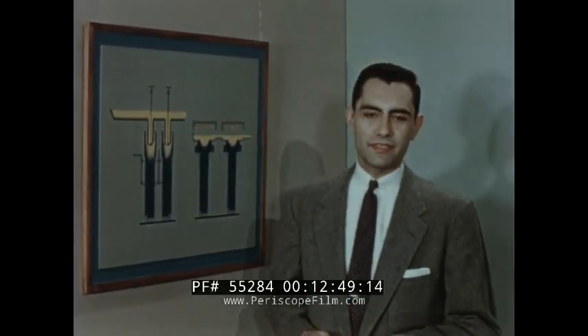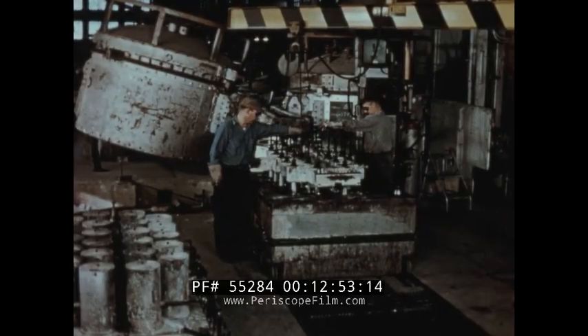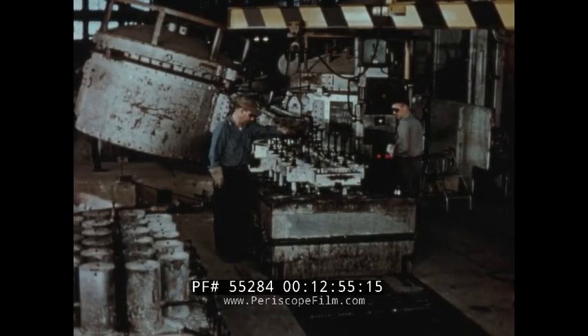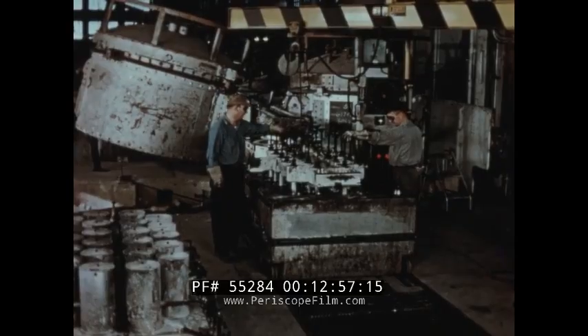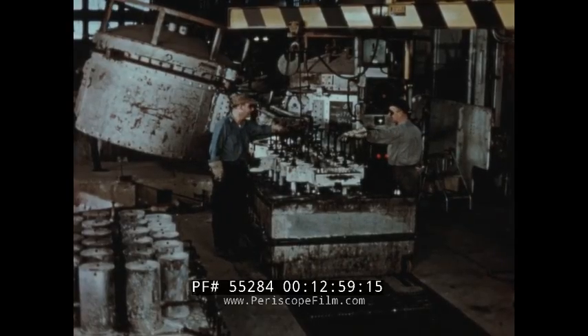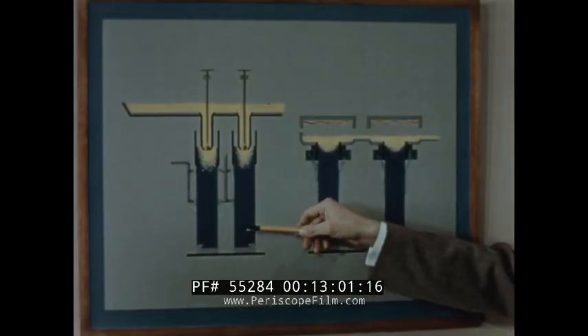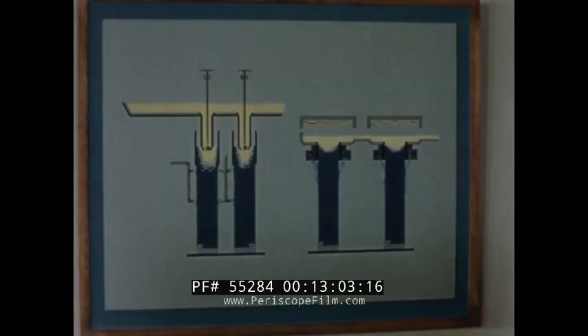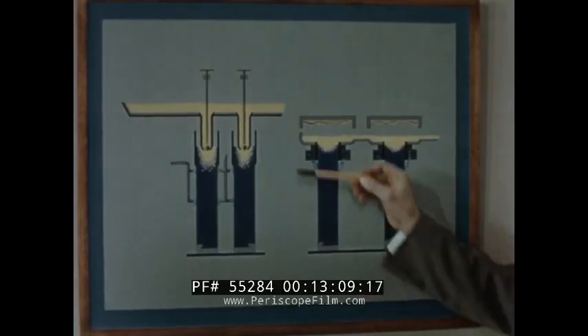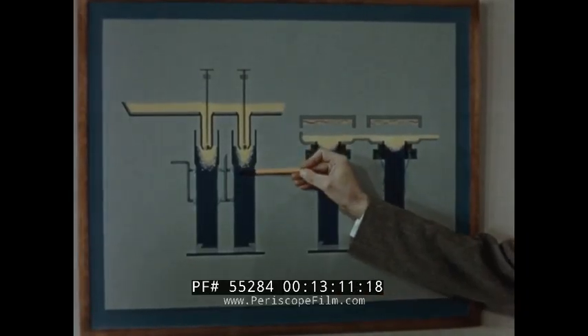Now, to produce DC ingots, the metal is poured into a trough, and from here it is fed into individual metal molds, which extend into underground pits. Water-cooled jackets around these molds cause the metal to solidify into ingots. As they emerge through the bottom of the molds, the ingots are further cooled with a spray of water.